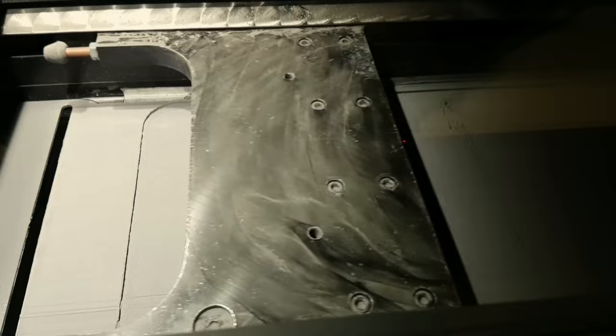And then the laser starts again, melting together the powder on top. As you can imagine, the laser operates at really high temperature. And so you have to do some additional processes, because every time the melt pool solidifies after the laser's passed over it, it contracts slightly, and that puts a lot of residual stress into the part.